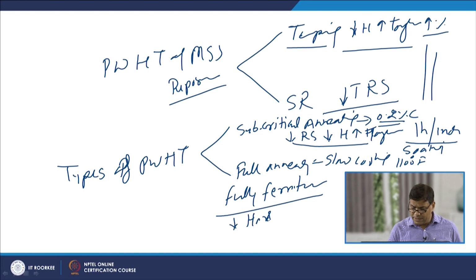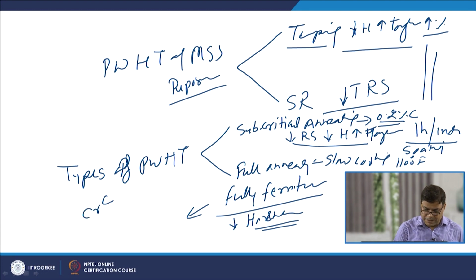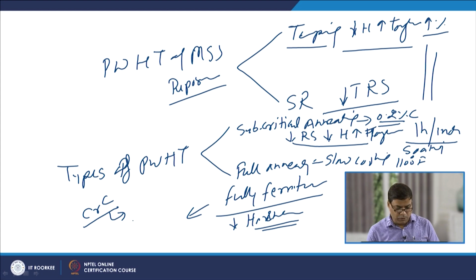So, when increased softness is needed, through the formation of the fully ferritic structure, full annealing is performed, but this process is quite long, because the chromium carbide present in the steel needs a longer time to dissolve to form the homogeneous solid solution in the austenitic state, followed by slow cooling up to 1100 degrees Fahrenheit. Thereafter air cooling can be performed.